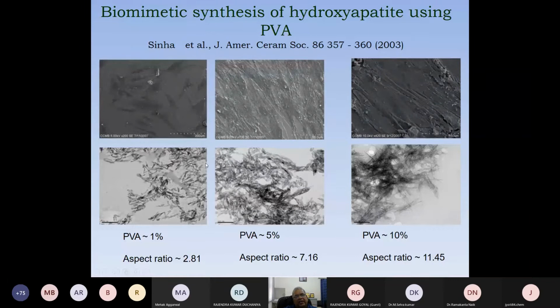So as I showed earlier, PVA has the tubular structure. If on that we nucleate hydroxyapatite, we can get the fibrous form of the hydroxyapatite. And if we change the concentration of our PVA solution, we can change the aspect ratio, which in turn changes the cell material interaction. So we synthesized hydroxyapatite in situ in PVA. We did not mix hydroxyapatite with PVA. Again, we synthesized hydroxyapatite in situ into PVA, and the bottom row shows that as we change the polymer concentration from 1 to 10%, the aspect ratio of the synthesized nanoparticle changes from 2.8 to 11.45.